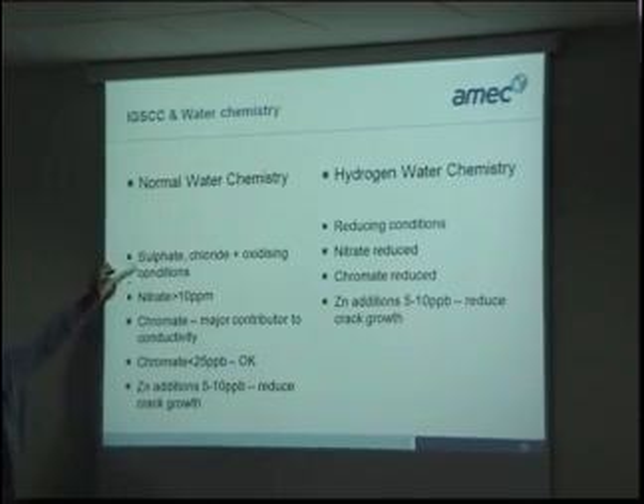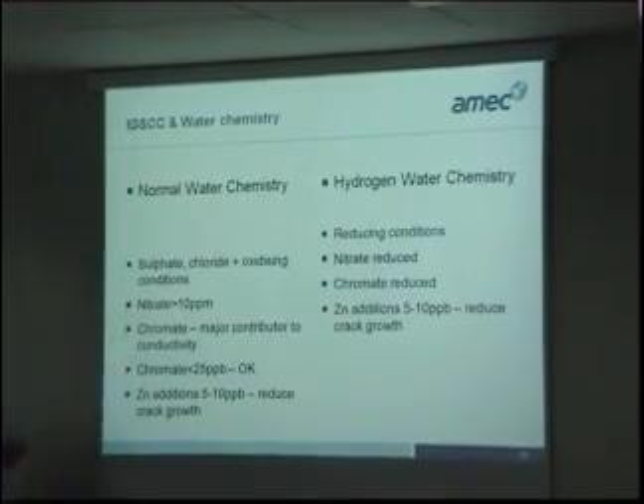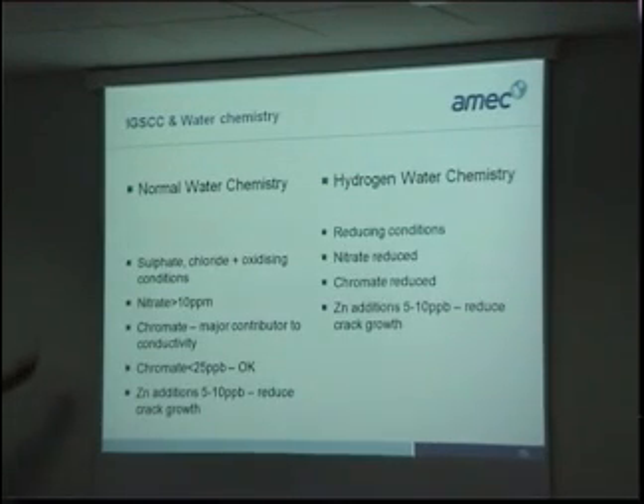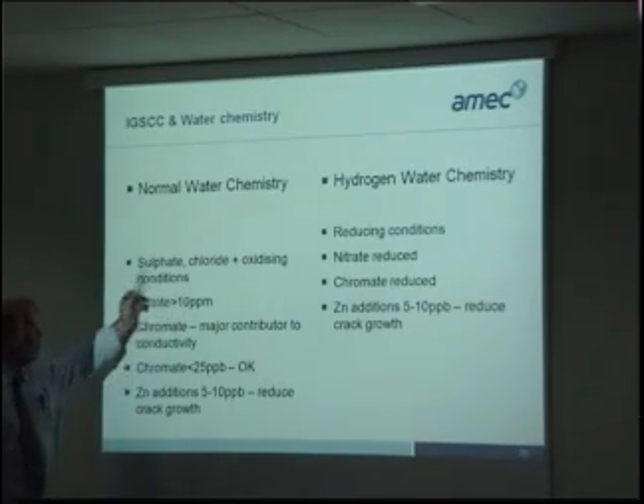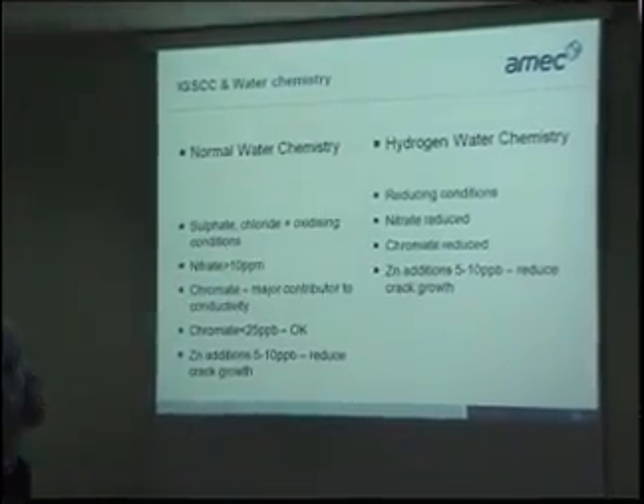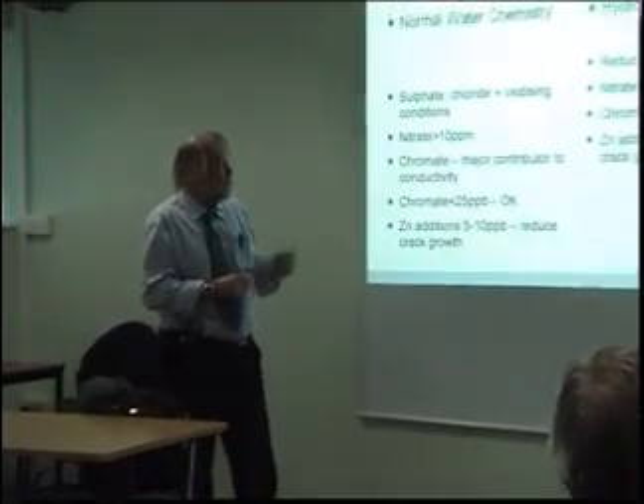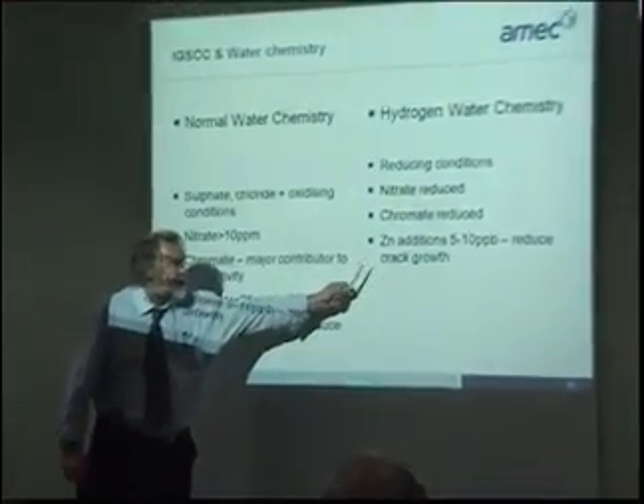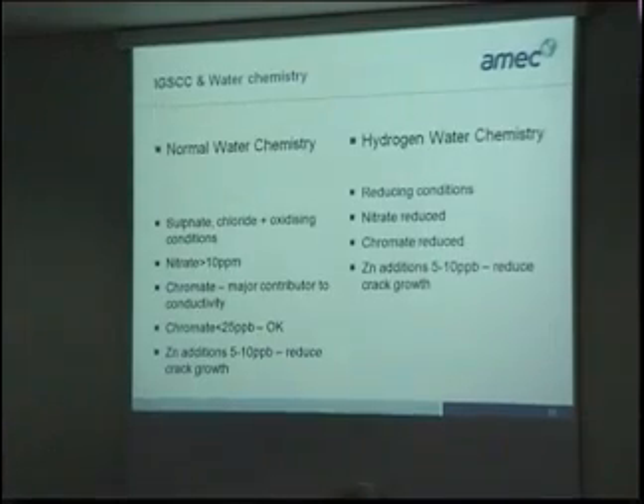So you've got your impurities in there, and you're in oxidizing conditions because the radiolytic field produces oxidizing free radicals, and it was found that chromates in fact were the major contributor to conductivity because of the chromium in the materials in contact. The chromate was about 25 parts per billion. Zinc additions were done here. Now obviously to change from oxidizing conditions to reducing conditions, you can add hydrogen. So later on this was done to maintain reducing conditions. Nitrates and chromates were reduced, and the zinc levels were maintained, and these were found to reduce the crack growth.